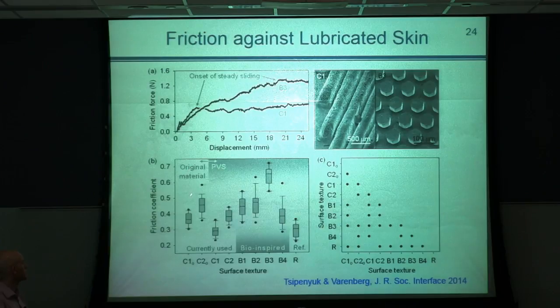And this is the summary of all the results, where friction coefficient is represented as a function of surface texture. So we have here skin stretching elements by Schick, by Gillette, made from original materials, but we had to cast similar structures from the same material because the idea was to test the effect of geometry and not the effect of the material. So we created the same geometry based on our material by molding, by creating templates against the original surfaces and then casting these structures made from our materials.